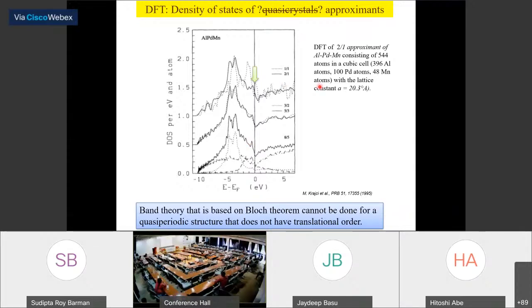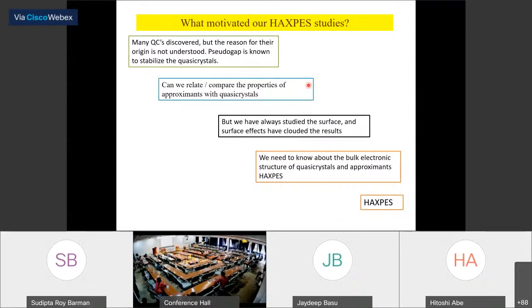But nobody has done a real quasi-periodic structure because band theory depends on Bloch's theorem, which does not hold for quasi-periodic structures, which do not have translational order. So what motivated us to do the HAXPES studies is to compare the properties of the approximants with the quasicrystals, see if there is any difference, because the theory cannot do the quasicrystals, and to see how the pseudo gap behaves. And we see how the bulk electronic structure evolves, and that's why we do the hard X-ray studies, because from low energy photoemission, there was not much information that we got.